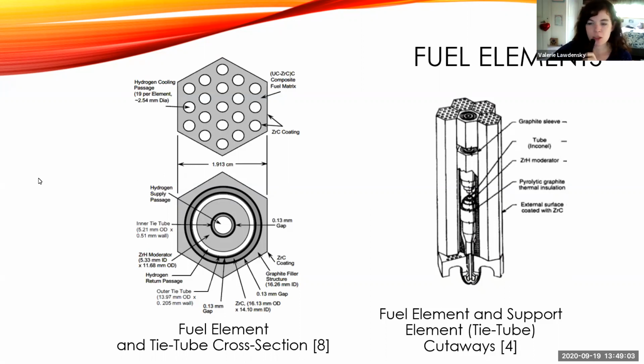These all have very specific parameters, but essentially the reactor itself just has a bunch of hexagonal elements that hold together very nicely. And the same size but different inside there is a tie tube, which is the very pivotal thing of my talk here. It has 6 concentric cylinders containing Inconel structural elements to hold the reactor together, as well as a flow channel that will go down and back up each element, and that's one of the early flow pieces where it's vaporized. And then that flow is used to power the turbo pumps that then push the rest of the flow through.